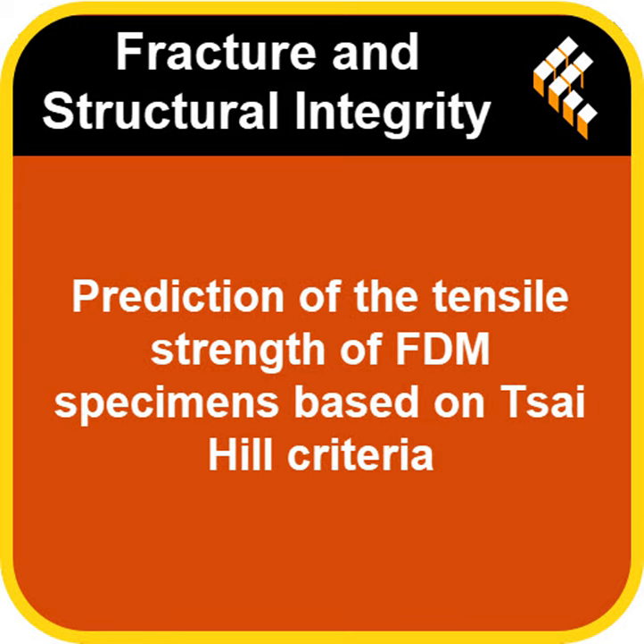And third, it's really encouraging to see that established engineering models, like the Tsai Hill criterion, can be quite accurate in predicting the tensile strength of these FDM parts, especially for the simpler, uncontoured structures. That's valuable for design. Yeah, predictive power is huge. Definitely. And finally, the utility of tools like DIC, it really gives us a much richer picture of how these materials actually deform and fail under stress, especially for complex tests like shear, where a simple extensometer might not tell the whole story.